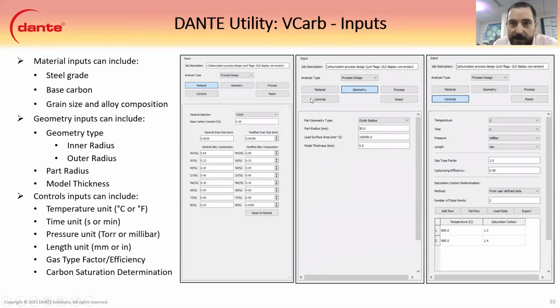It also has, like I said, material, geometry, and controls inputs. So the material inputs use the DANTE material database. Right here we use 4120, so it's 41XX, and then it's 0.20 base carbon. And then we have a grain size calculation and nominal and modified alloy. So if you have a different alloy melt, we can account for that, and it'll change depending on the alloy melt. For geometry, we have a geometry effect. So an outer radius and an inner radius will accept carbon at different rates. And so we applied that geometry to it.